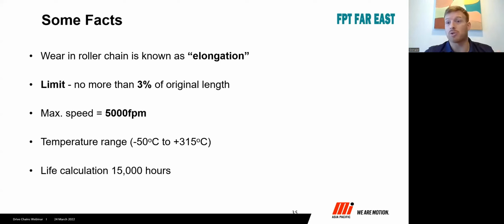So temperature, again, up to 315 degrees without too many changes to the base material, and minus 50 degrees. But for those, you need to consider the type of lubrication. If the temperature is really low, or really high, you need to consider the type of lubrication. And then we look at about 15,000 hours for operating life. That's a common gauge. That means if the drive is running very high speed and the distance between the sprockets is short, that affects your lifetime expectation. So then when doing the selection, you need to select appropriate chain that will give you a reasonable lifetime.